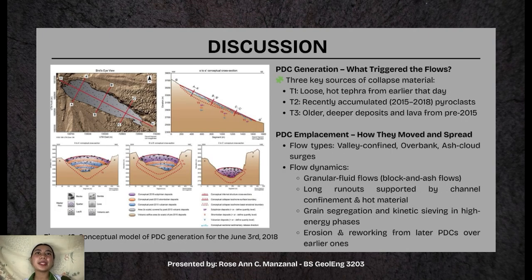The June 3rd PDCs weren't just the result of one big collapse, but a series of sequential failures that grew more destructive over time. Early in the eruption, the summit explosions deposited hot, loose tephra along steep slopes. As the day progressed, this unstable material, along with layers built up from previous years, collapsed under its own weight, especially after being hit by ballistic debris.